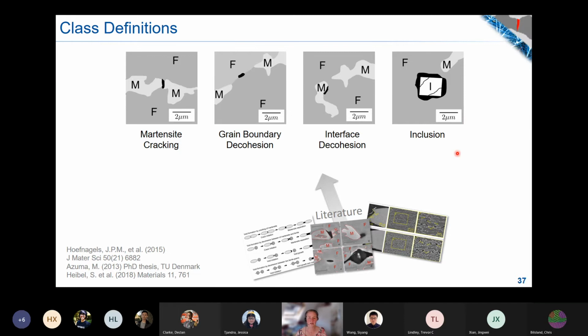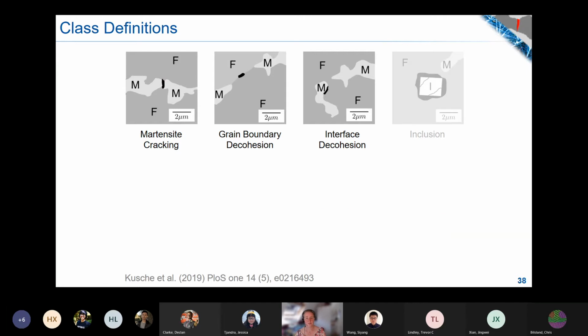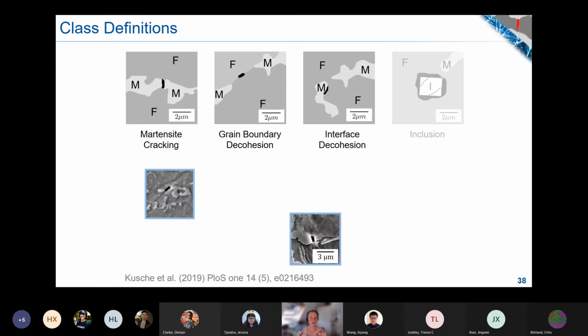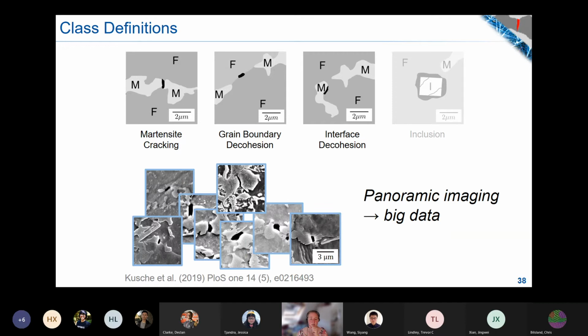You have inclusions, and we might not be interested in those unless they have decohesion here, but you can have interface decohesions, you can have decohesions at grain boundaries, or you can have the brittle phase breaking. That's what happens here, and this is what's shown in lots of images in the literature for dual phase steels. So that's where we left off.